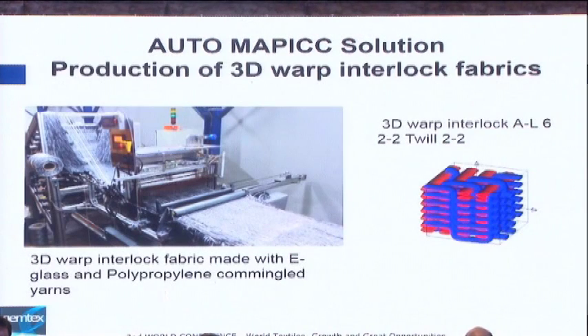Okay, so taking that into account, we have designed our own machine for making the 3D warp interlock structure. This is one of the machines we have designed completely. And thanks to that, we have been able to make some pilot scale production. It's not a large scale, but pilot scale. It is based on the main motions you can find on Dobby weaving machines. The type of 3D warp interlock was an angle interlock with 6 layers based on a 2x2 twill.